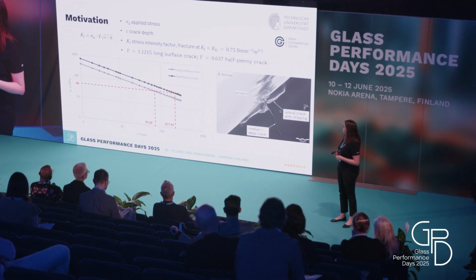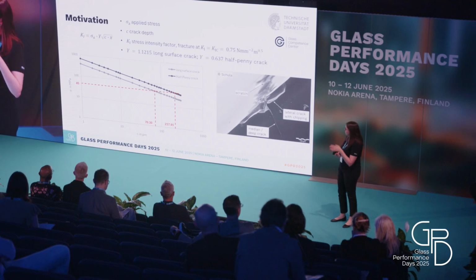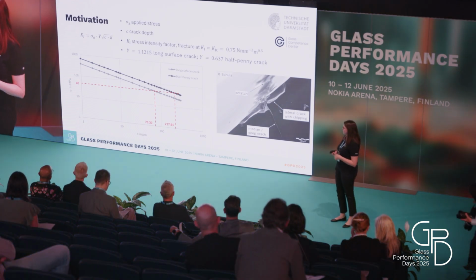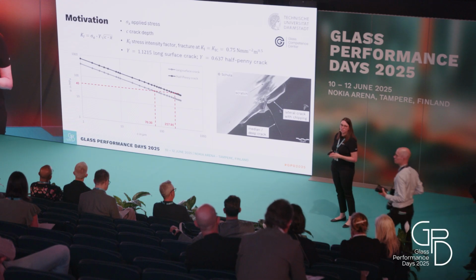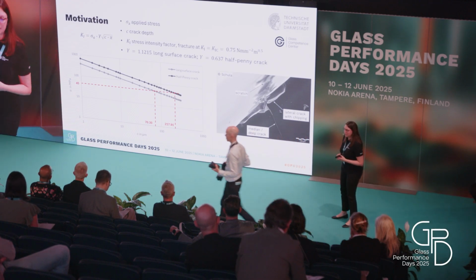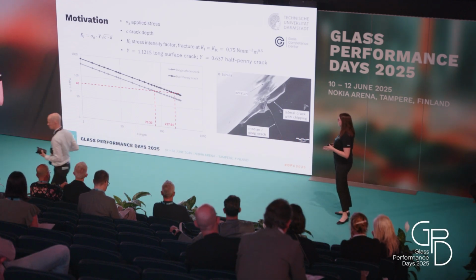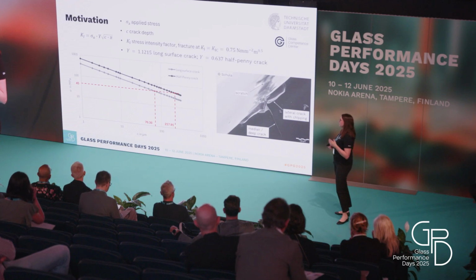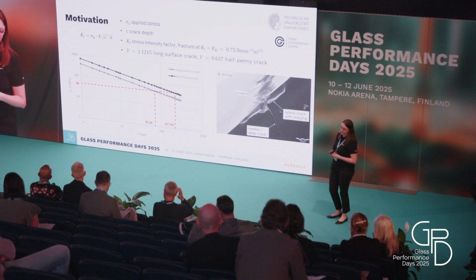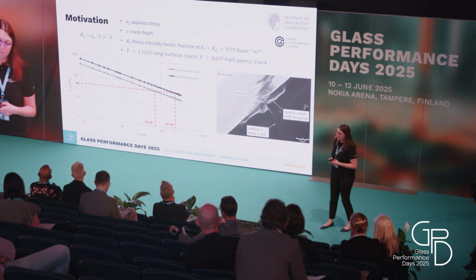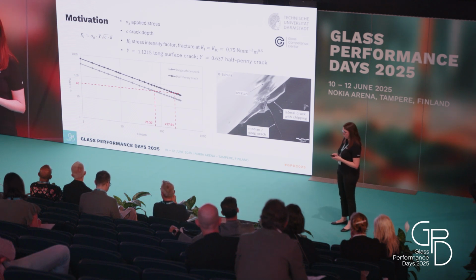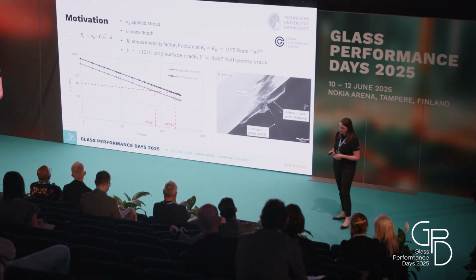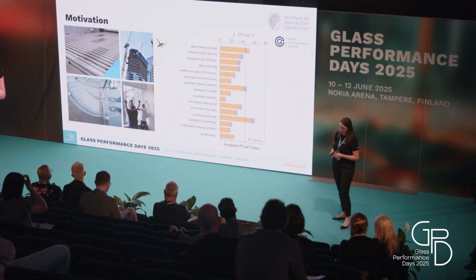And I also marked the 45 megapascals on the y-axis, which is the stress that I want to apply without failure. And here we see that for the long surface crack, the depth of the median crack is limited to 70.3 micrometers, so that no failure occurs, which is quite small actually.